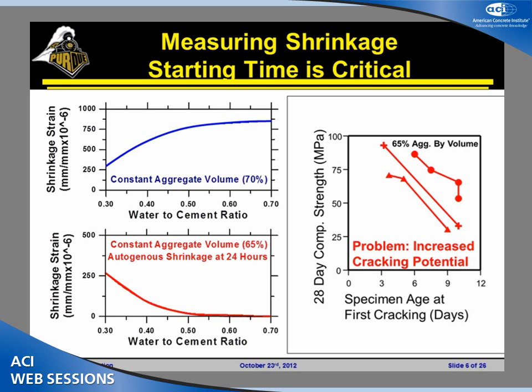And what I want to argue and what I want to put forth is this is the autogenous shrinkage that's occurring throughout the cross-section. So it's uniform across the cross-section. This is also the autogenous shrinkage that we're not accounting for if we just have a spray-on film, because it's not due to evaporation. It's due to chemical shrinkage and self-desiccation. And the other thing I want to point out is if you add this 250 in here, this line becomes really flat. Right? We see that shrinkage is really not as related to water to cement ratio as this graph would lead us to believe, but it's really more related to paste content and water content. And as a lot of people go to get these higher strengths, they increase the paste content, which means they're going to increase the shrinkage in the overall system.